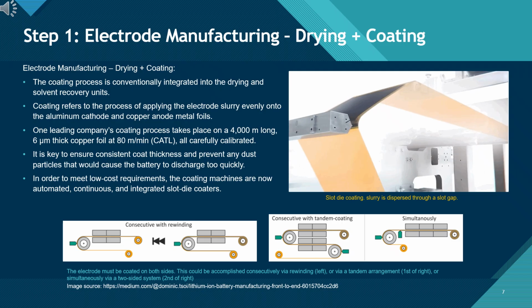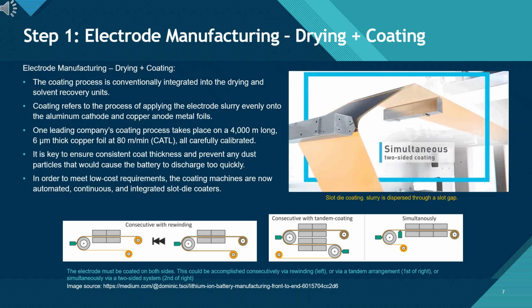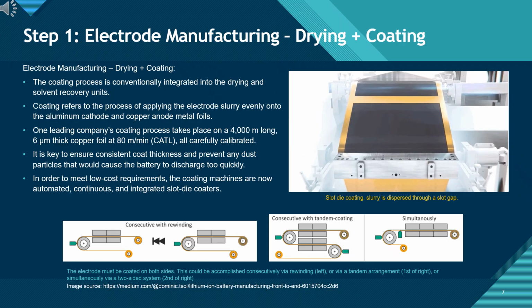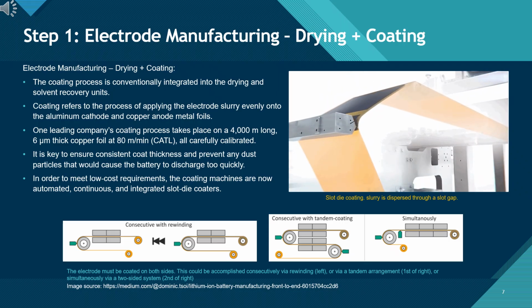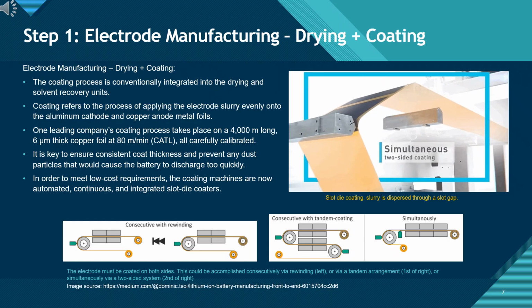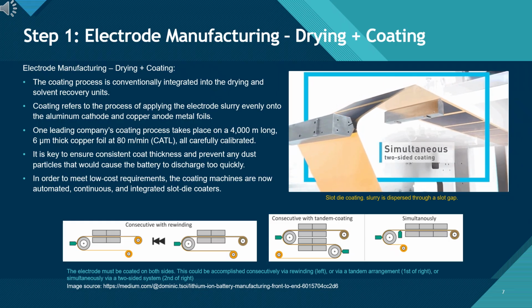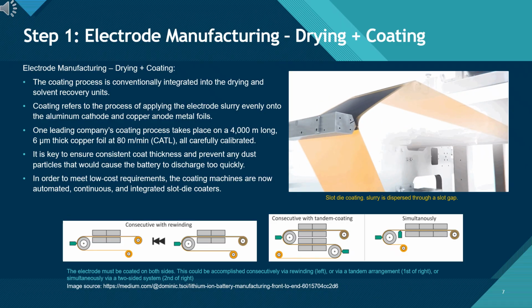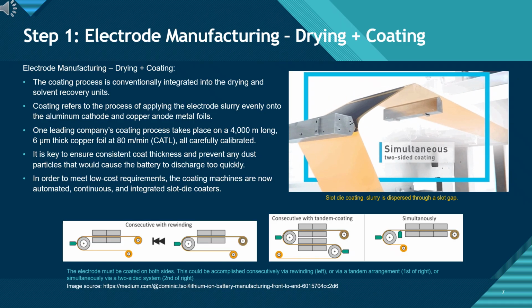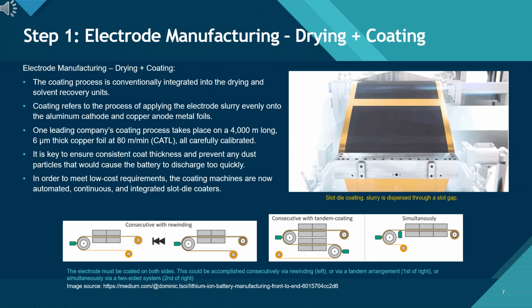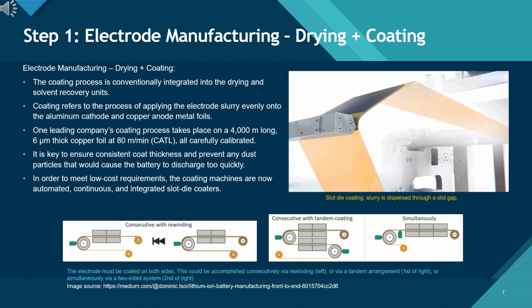The next step after mixing is coating and drying. In this process, the slurry is spread evenly onto copper foil for the anode or aluminum foil for the cathode. Slot die coaters, like the one shown here, apply the slurry through a narrow gap, ensuring a uniform and precise layer. Coating machines in modern factories are massive. At CATL, for example, slurry is coated onto copper foil that's 6 micrometers thick and runs nearly 4 kilometers long, moving at speeds of about 80 meters per minute.